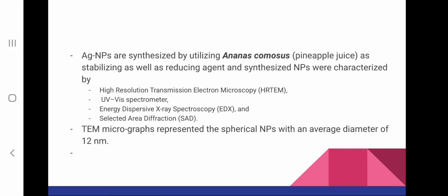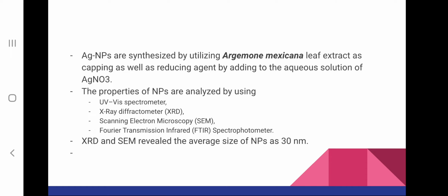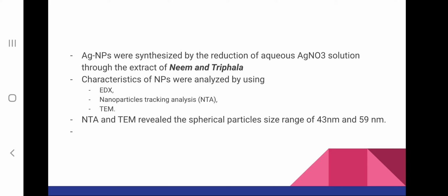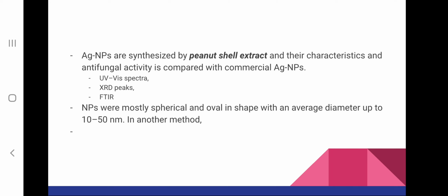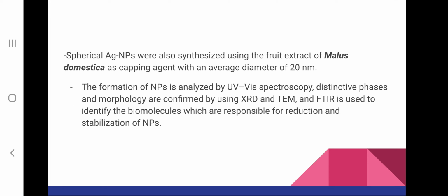utilized for synthesis of silver nanoparticles, and the synthesized particles were characterized using different tools, and nanoparticles of size 12 nanometer were obtained. Then by using Argemone mexicana leaf extract, nanoparticles of 30 nanometer size were obtained. Then by using neem and triphala, with aqueous silver nitrate solution, nanoparticles of size range 43 to 59 nanometer were obtained. Using peanut shell extract, nanoparticles with diameter 10 to 50 nanometer were obtained, and these nanoparticles had antifungal activity. And using Malus domestica, nanoparticles of 20 nanometer were obtained.